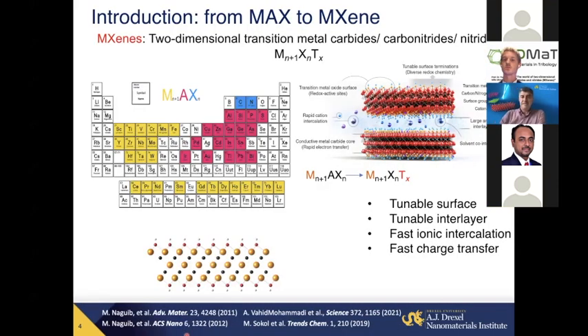So what are MXenes? MXenes are carbides and nitrides of transition metals. The name actually came initially from their precursors, MAX phases. My colleague at Drexel University, Professor Michel Barsoum, is the father of that field of layered carbides and nitrides. X stands for carbon or nitrogen, M stands for a transition metal from this group, and A is one of the elements of this group here. What we basically do to make MXenes, we remove the A element from MAX, and what is left is MX. As a result of this etching, oxygen, chlorine, fluorine, and other elements are added to the surface. So Tx stands for these surface terminations.